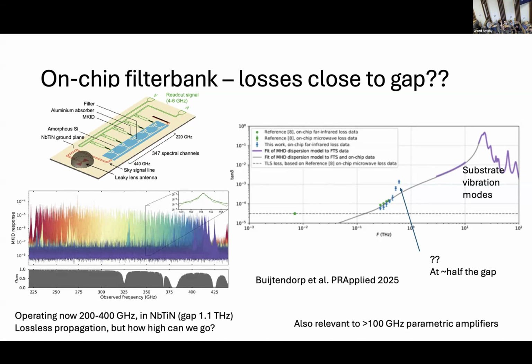The interesting part is: what is the loss on this line here? And the point is that we are not looking into the losses that, like Florence has shown before, where the loss is about the same order of magnitude as the loss above the gap energy. Here we want to have this thing travel hundreds of wavelengths before being absorbed. So we want a Q of more than 1,000 or so. Otherwise, we lose the signal before it's even detected.